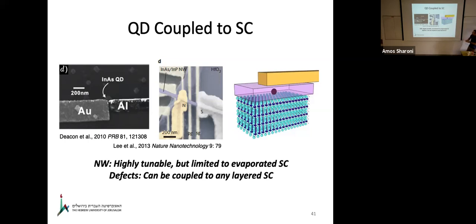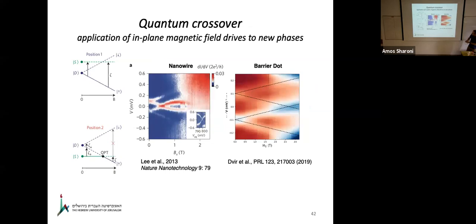And what people saw, in a study for example from the group of Silvano De Franceschi, is that you can see these states which are called Andreev bound states. They are related to the fact that if you want to add carriers into a defect where superconducting correlations are involved, then there's a singlet state and a doublet state, which can split under the effect of magnetic field. At a finite magnetic field, there's a quantum phase transition, which appears here.